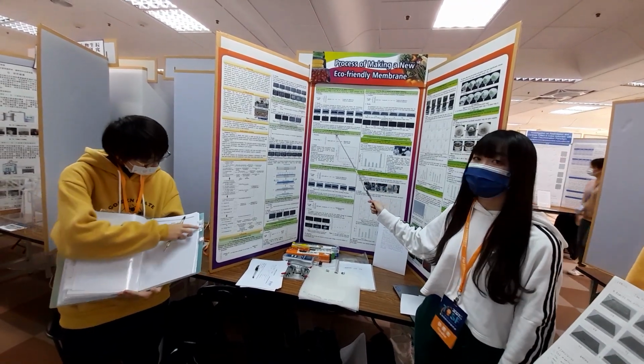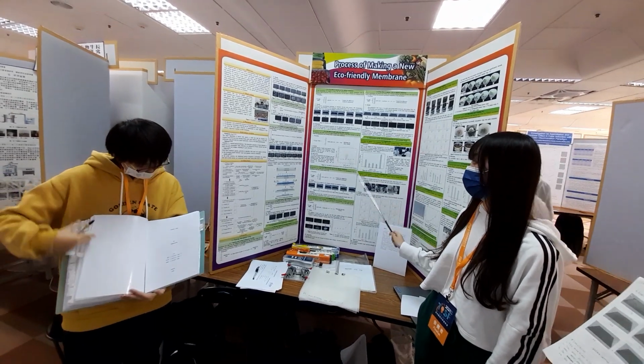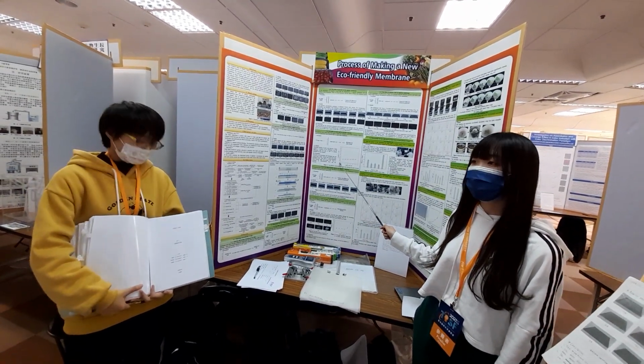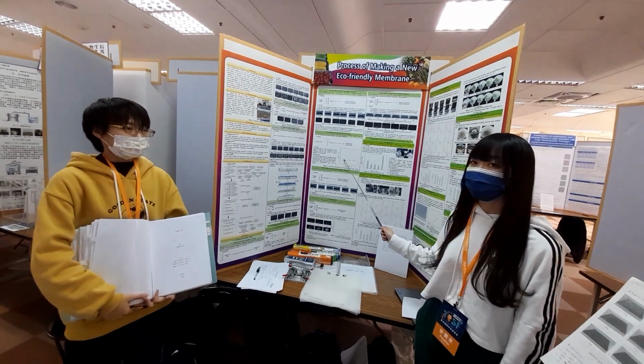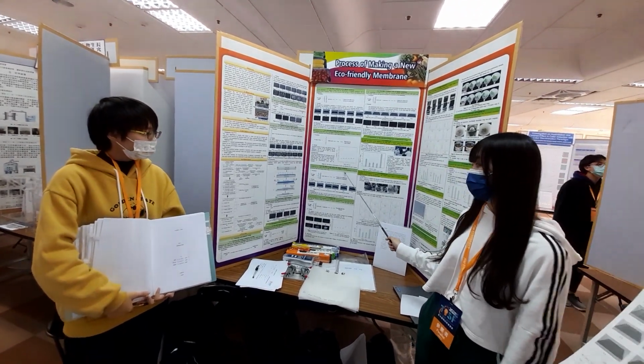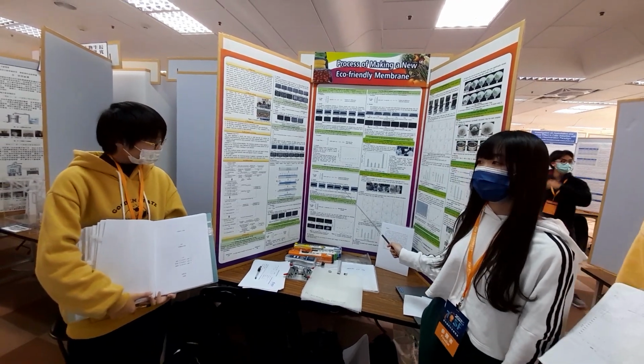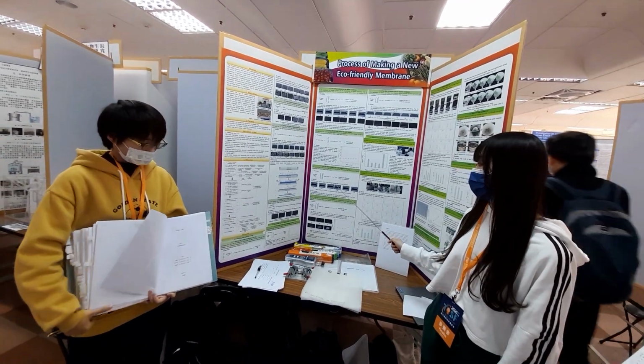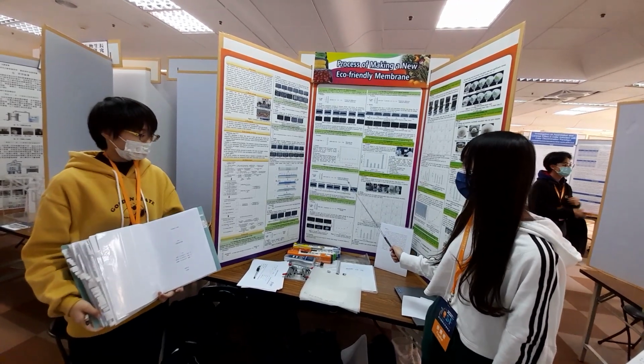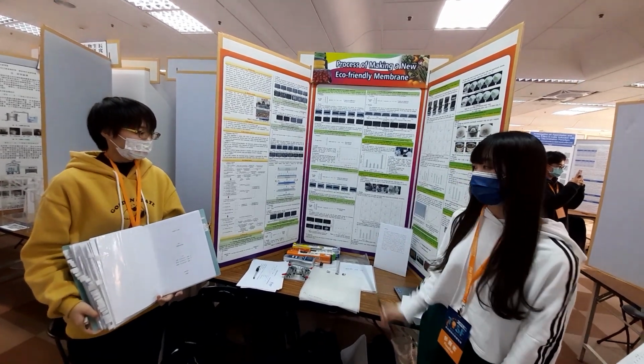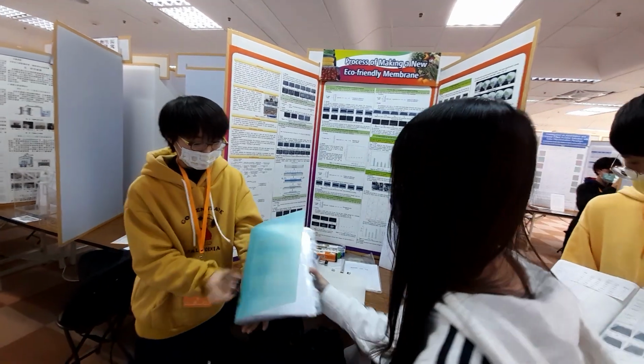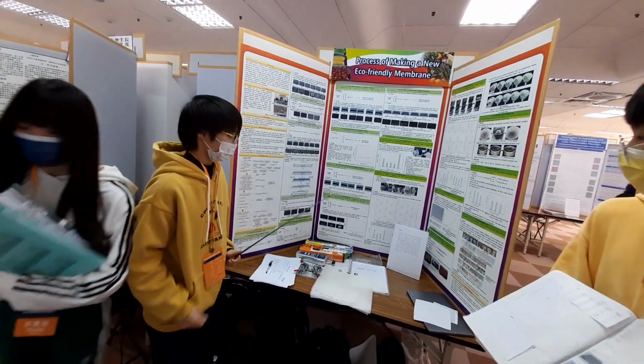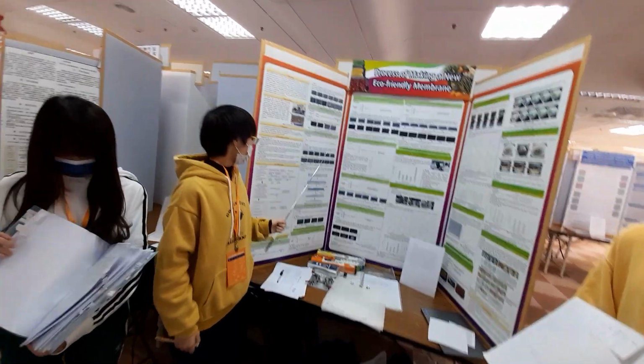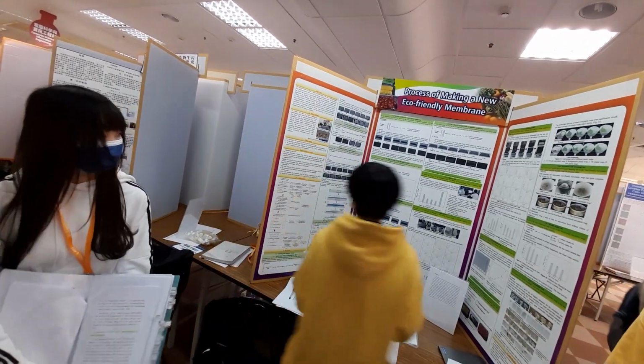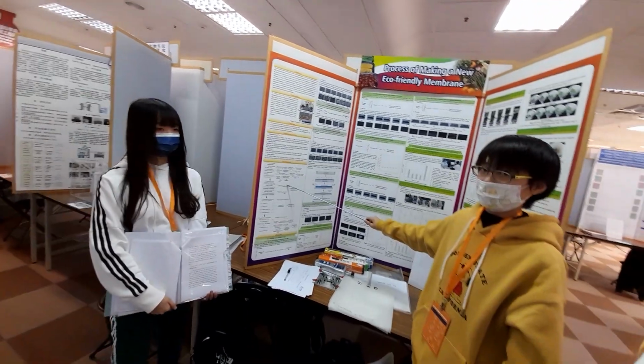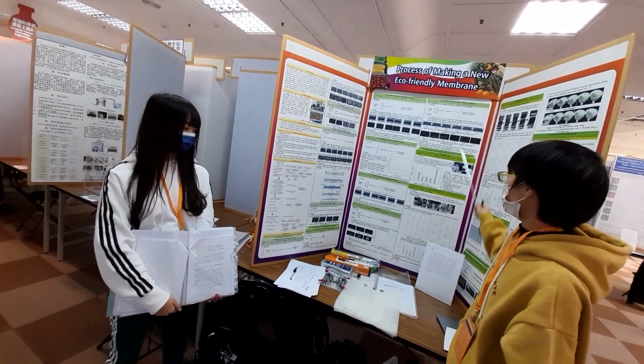Then we started to discuss the effect of acetic acid on paste viscosity. As the concentration of acetic acid increased, the paste viscosity increased as well, and we make it into the membrane. The acetic acid improved the strength of the membrane. So after we add more acetic acid, the membrane becomes stronger. We discuss whether acetic acid and glycerin influence paste viscosity and membrane.